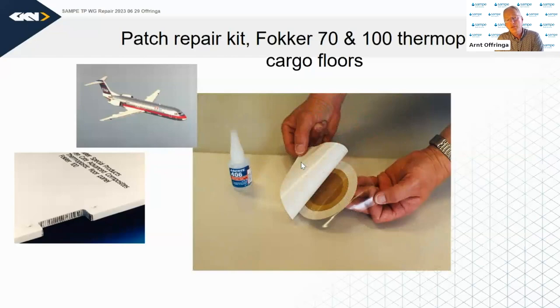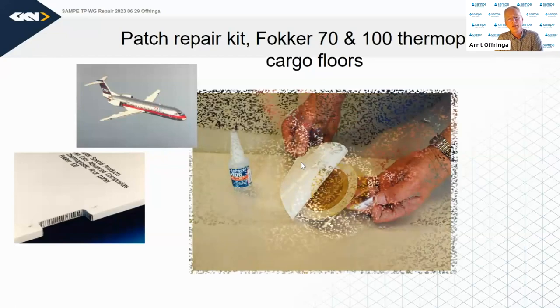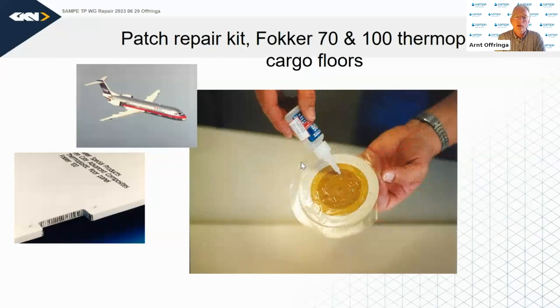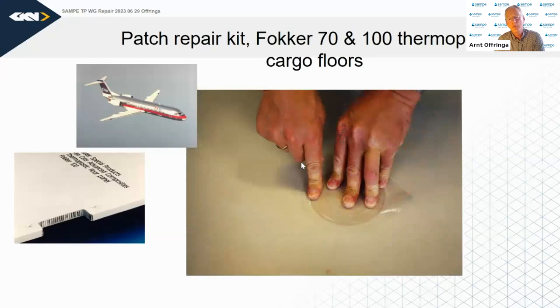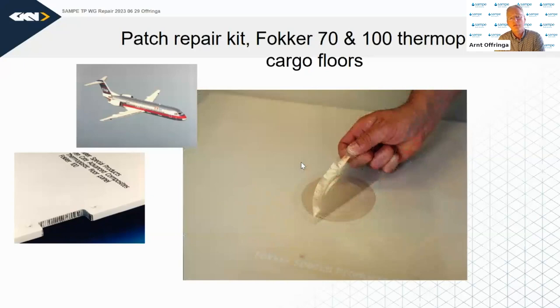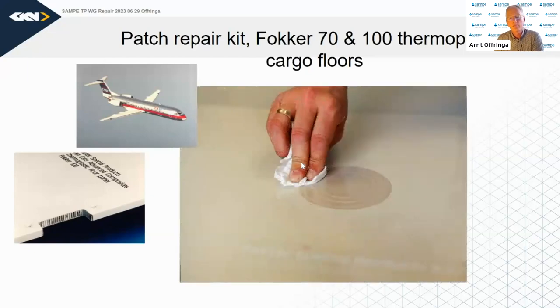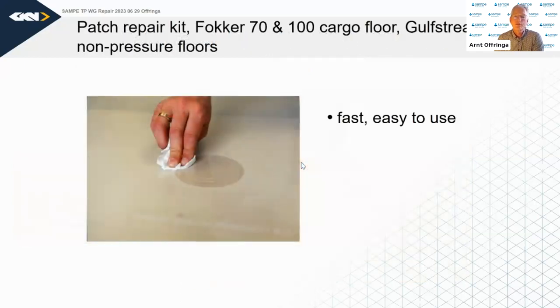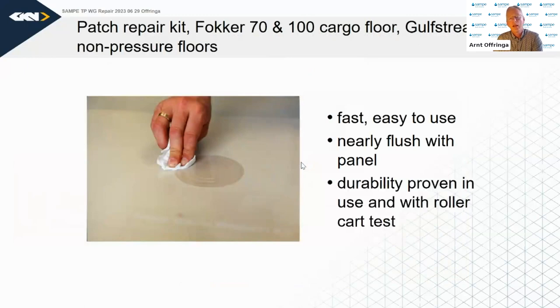And as you can see on the pictures, it had several colors, so dark brown, light brown, and whitish color. So there are three layers there of a quarter millimeter each, stepped layers. You apply the Loctite cyanoacrylate adhesive, which is a very fast adhesive. And then basically you push it on with a plastic foil, and afterwards you pull off the foil, and you're done. And this repair is very durable. Luggage is moved over this, and the repair has to stay on for a long time. So to conclude, it's fast and easy to use, almost flush with the panel, and durability was proven with a so-called roller cart test, which is a roller cart loaded with weights that rides over the repair area to see if it's durable.